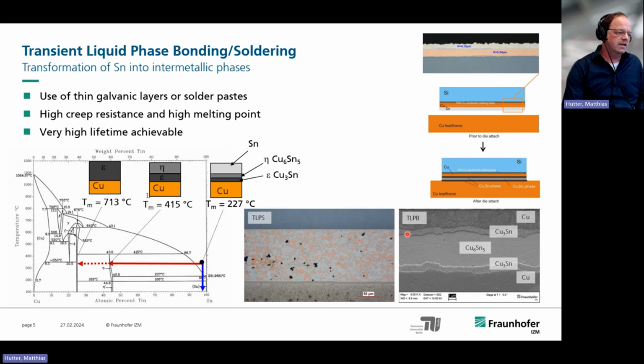The transient liquid phase bonding is also a sort of, let's say, soldering, because it's more or less a solder joint, but the special thing is that the tin is totally transformed, or at least almost totally transformed, into intermetallic phases. You can either use paste, where copper particles are in the paste, or you can use galvanic layers. You see very thin layers. You put it on, in this case, a copper lead frame or also a DCB substrate, AMB substrate. And then, because everything is very small, the gap is very small, we have a very thin solder line.